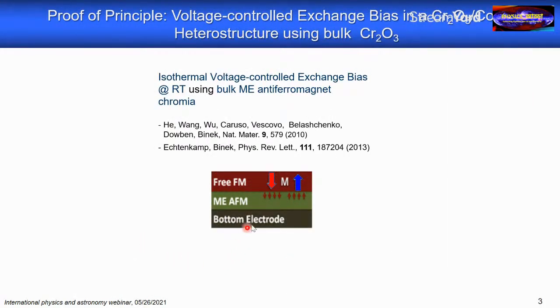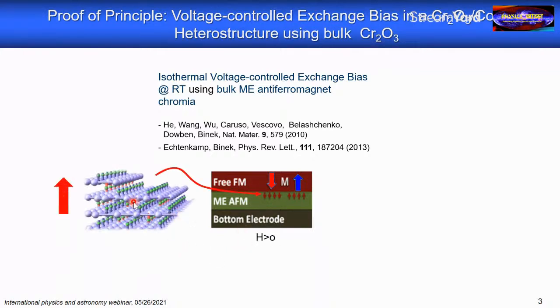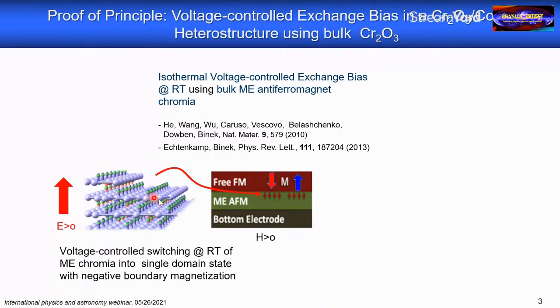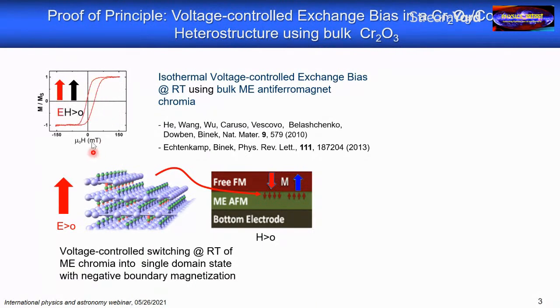We used a commercially available single crystal of this material, so macroscopic bulk, and deposited a thin film of cobalt palladium on top of it. And we could show that indeed there's this boundary magnetization which couples to the ferromagnet, and that we can switch by rotating the electric field.